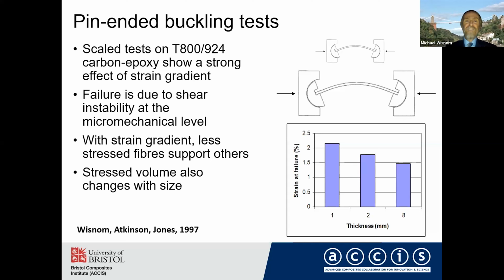And really, in this case here, failure is due to a shear instability at the micromechanical level. What we think is happening here is a strain gradient effect: the fibers which are less stressed away from the surface support the other more stressed ones and therefore inhibit the instability failure. Whilst we think this is largely an effect of strain gradient, by changing the specimen dimensions you're also changing the volume of stressed material. So we can't really separate those two effects in these tests.